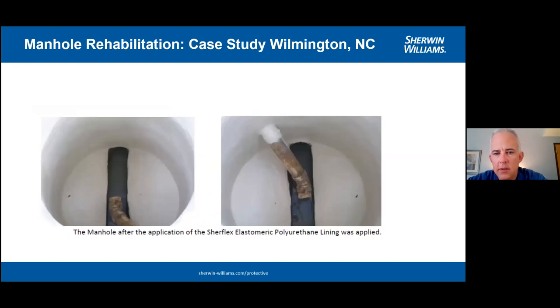And here's the finished product. So the system as applied on this is a cementitious rehabilitation and then an approximately 1/8 of an inch thick protective liner put over the top of it, to where, again, we're going to be in that 30-ish year life cycle before this manhole has any level of corrosion going on within it again.